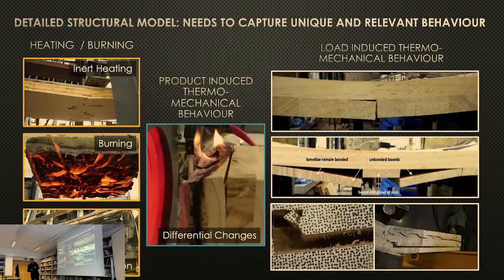Okay? And when you start looking at these complicated products, you're going to have different forms of mechanical failure. You're going to have, obviously, burning. You're going to have charring, potentially extinction. But you're going to have product-induced thermomechanical behavior. So, for example, when you start heating this, the material that is being heated, as it loses moisture, is going to contract. And the moment it contracts, the glue lines or the adhesive lines become failure modes. And basically, you have material that splits. This is called delamination. And the splitting of the material results in pieces of timber falling down and feeding the fire. So it increases your fuel load, and therefore creates a bigger problem.